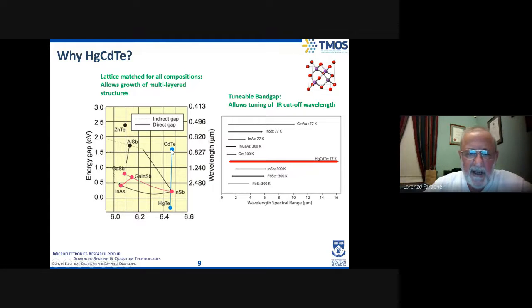And the important thing is, this is almost a vertical line, which means the lattice constant virtually does not change. So it doesn't introduce any stress in the semiconductor crystal or generate defects if I vary the composition within the device structure.